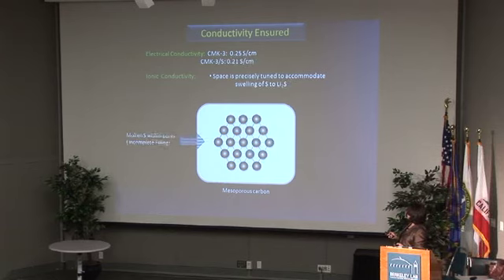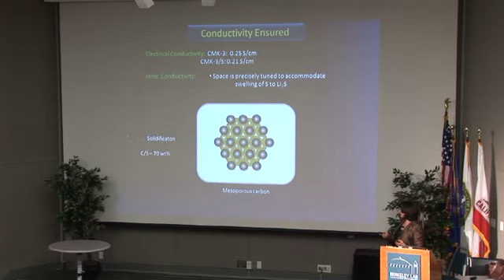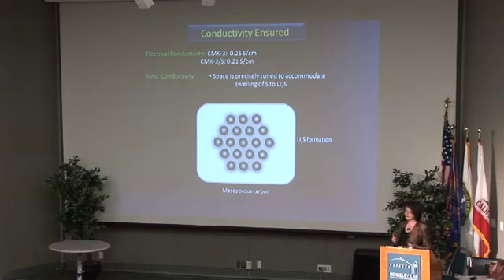And the sulfur fills this space. When we melt it inside, it imbibes by capillary action. And we tune the space to accommodate the swelling of the sulfur to form the Li2S. So we actually leave space here for the electrolyte ingress. Ultimately, on solidification, when the Li2S is formed, it completely fills the space. And this enables the back reaction to occur, in other words, the reaction of Li2S back to elemental sulfur. Because both elemental sulfur and Li2S are extremely good insulators, that level of contact is necessary in order to actually activate the electrochemical reactions.